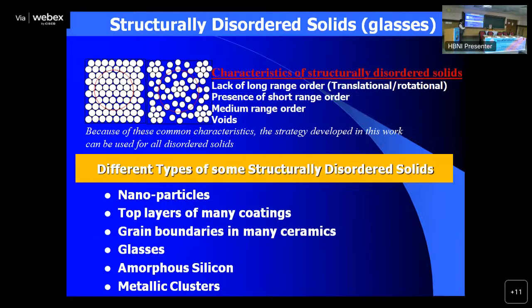And then it has medium-range order. Glass has medium-range order, and this is the order which has not been studied well, because of the difficulties associated. And you also have voids. This is the structure of a crystalline metal, and this is a non-crystalline metal. You have voids because the density of glass is less than that of its crystalline counterpart. So you have lesser density, and that is because of the voids. The voids are located at the end of the medium-range order domains. So this is the structure of disordered materials. Because of this common characteristic, the strategy developed in this work can be used for disordered solids of all types. To study glass, you can use the same strategy for other disordered solids also.